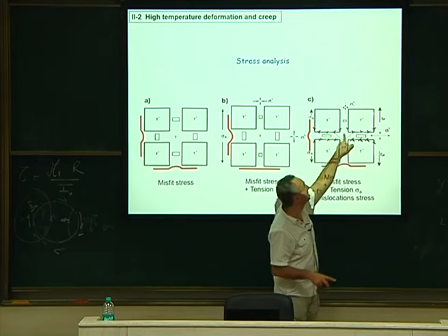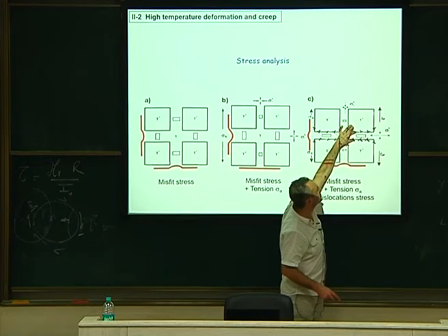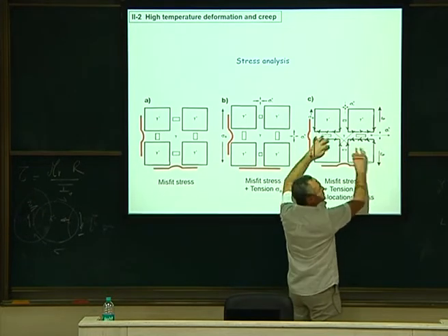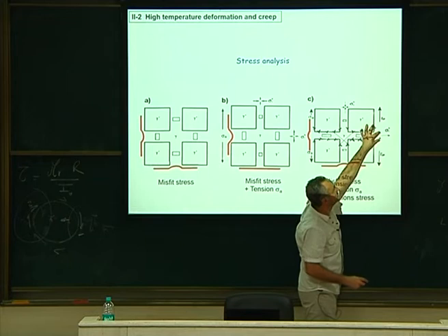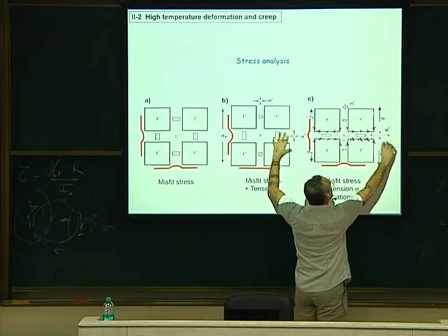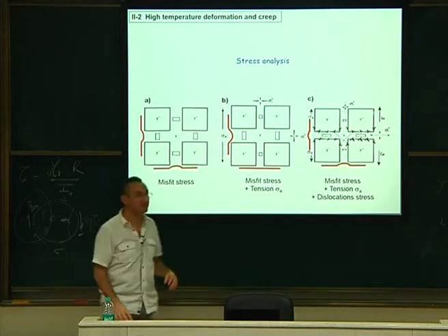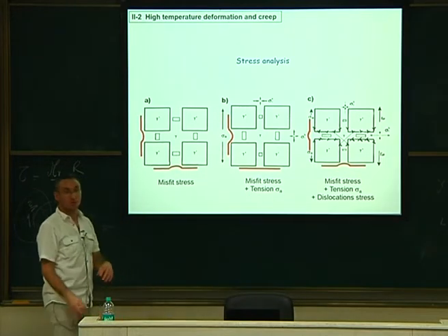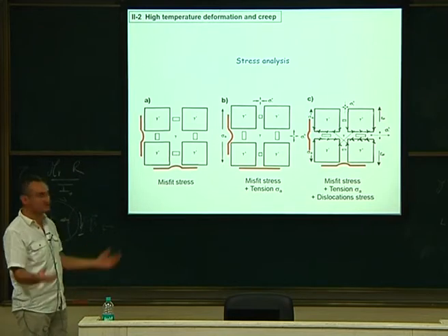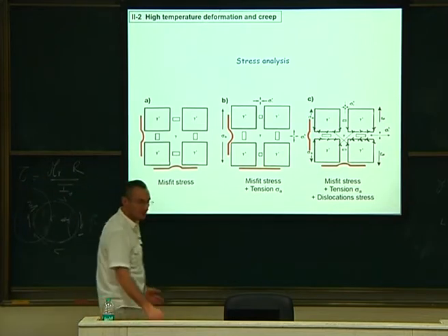Interfacial dislocation network here. And this dislocation network generates a stress, which is a big tension stress in this direction, like that, and a few on that one. So this expands like that and constricts the full specimen. So this was the origin of this negative creep, which was controversial for years, actually. Since the 60s, it was observed, and nobody knew why it was like this.